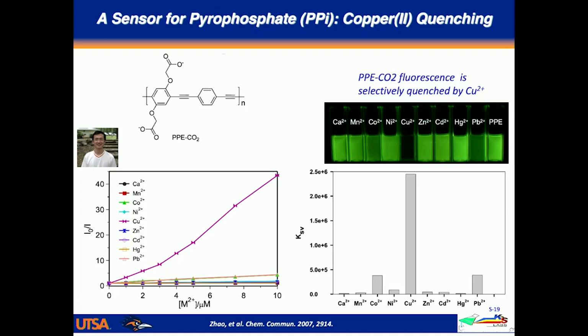No, it actually has to do with just binding to carboxylate. It is acting as a redox quencher. It's an electron acceptor, but it turns out nickel or cobalt can also be electron acceptor quenchers. But if you look up in a table of inorganic chemistry stability constants, divalent copper among all these metal ions has the most stable binding to carboxylate. So it's really the effectiveness at which the carboxyl brings the ion to the polymer backbone, and that's what dominates.